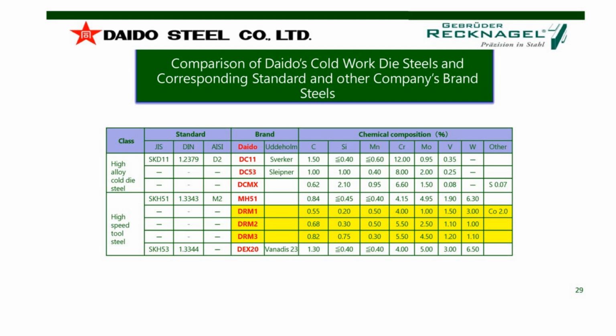Dream 2 is our newest steel grade with Recknagel Präzisionsstahl. We started in the market some months ago. Dream 2 has a really high hardness of 62 HRC in combination with a very high toughness, and the chemical composition is about 0.7% carbon, and the carbide building elements are also a little bit limited: up to 5.5% chromium, 2.5% molybdenum, vanadium about 1%, and tungsten also 1%. And it reached a hardness of 62 HRC.